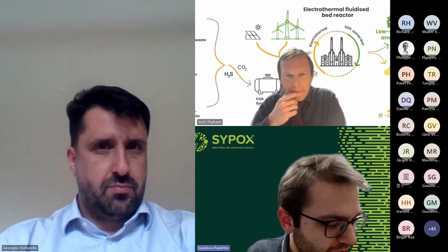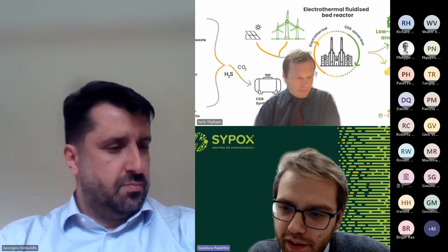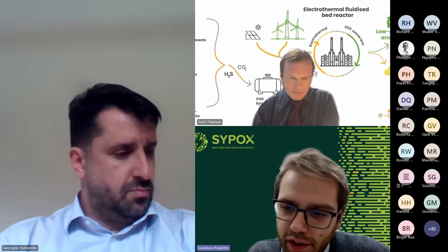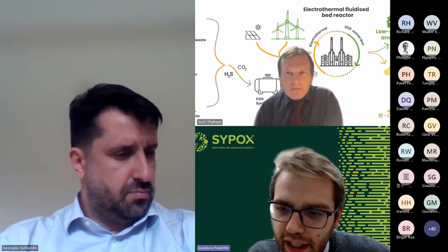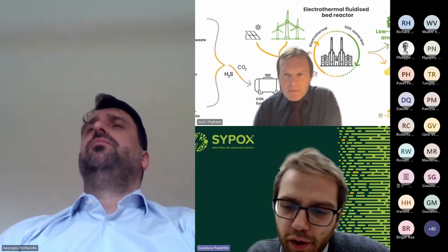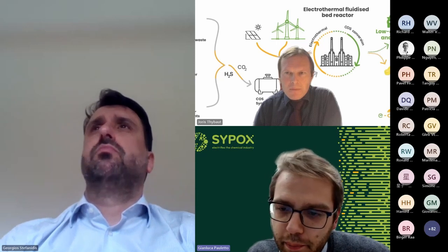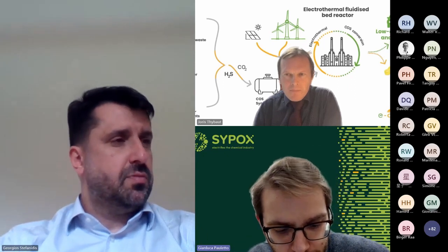Yeah, absolutely. So for the atmosphere that we are having in reforming, we did not have a problem with potential metal dusting or anything like this. Mainly it is because the heating element is able to withstand very high temperature, because the heating element is forming a surface layer of a compact material that is afterward preventing further oxidation, or the potential diffusion of carbon going into the heating element itself. And this is a property of the material that we are using, but that is normally used in a heating element, where you are mainly having nickel chromium heating element or iron chromium alumina material.